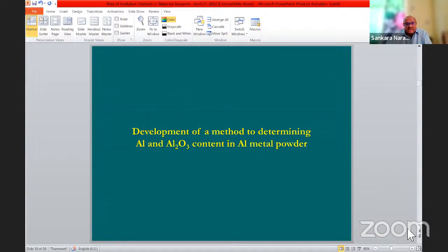The customs department took the sample and sent it to us, and asked us to determine how much aluminum and how much aluminum oxide were in the powder. It was a challenging problem because aluminum normally undergoes aerial oxidation and is covered with a thin layer of alumina.